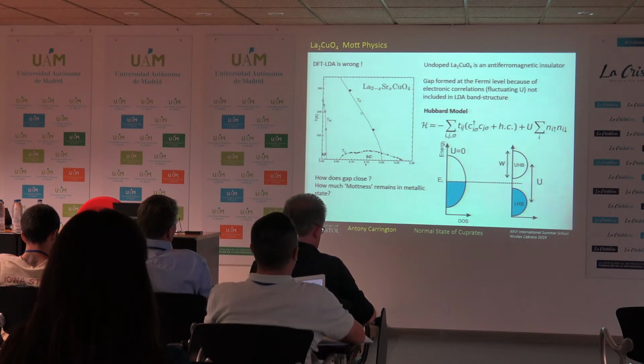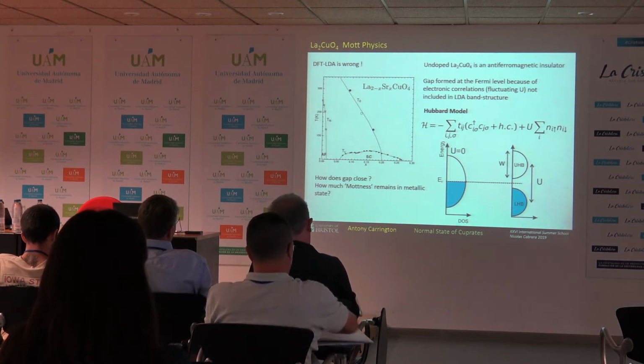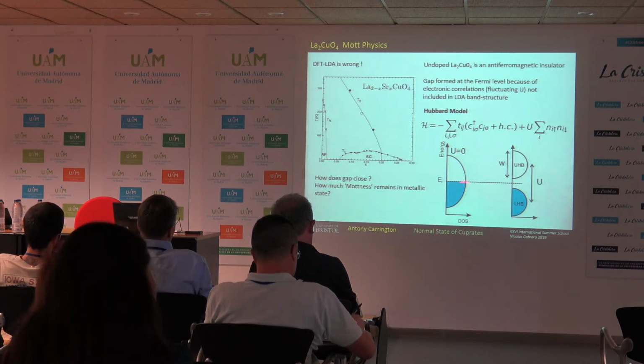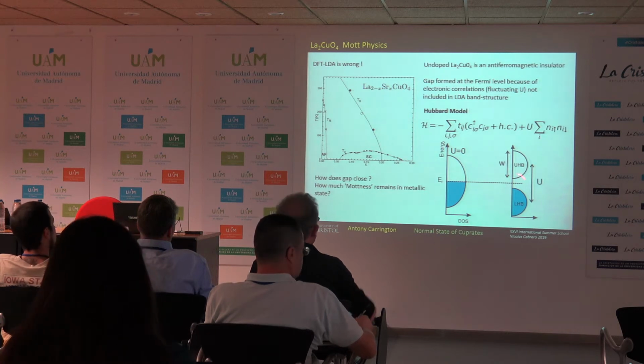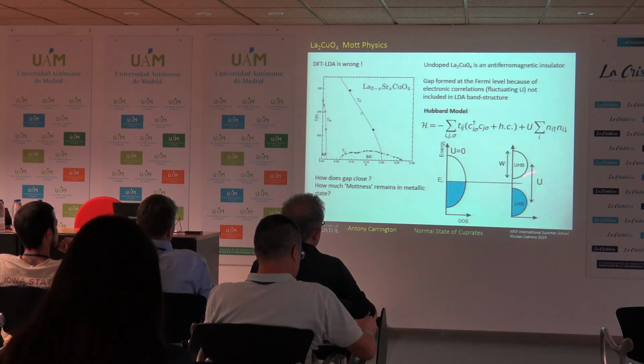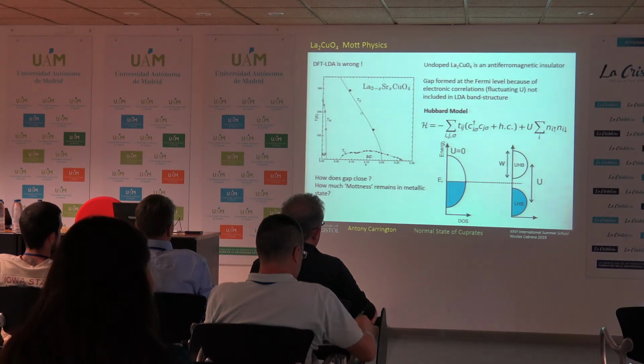So in the lanthanum copper oxide, you have 1 electron per site, and therefore it should be a half-filled band and good metal. But in fact, this is split into 2 by the Hubbard U, and you get a completely filled lower Hubbard band and a completely empty upper Hubbard band, and the Fermi level sits in the middle, and it's an insulator. Okay, so that's sort of the very basics.